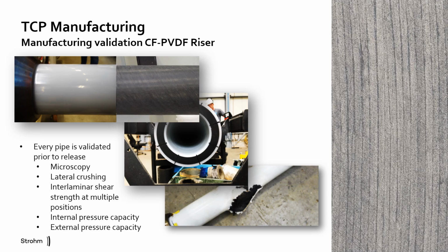For the riser system, we have several more options in terms of material. On the previous slide, I mentioned that using the riser layup leads to increased stiffness of the pipe and may lead to an increased MBR. This is not a problem because again it's all about balance. To counteract the trade-off between tensile strength and stiffness, and in partnership with our key material supplier, we have developed a higher performance tape option which gives us increased strength exactly where it's needed to reduce the MBR. The qualification for this material is already underway, and we have plans for the full riser system qualification in the very near future.